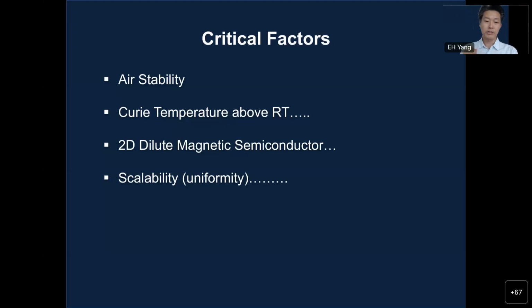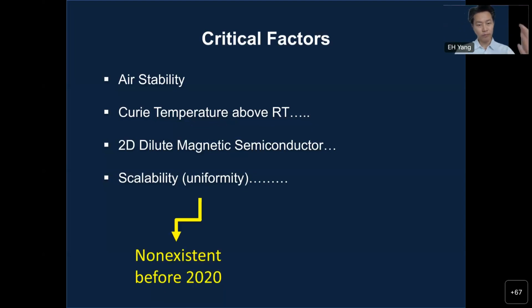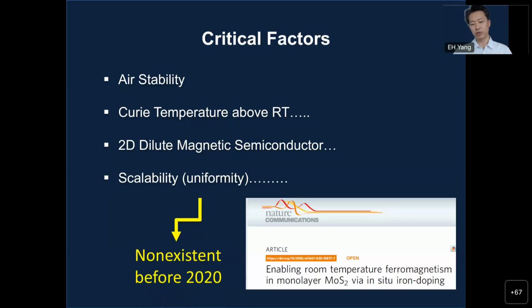Scalability: if you use the Scotch tape method to get these 2D materials or 2D magnets, it basically offers zero scalability. You need to provide scalability to some extent, and also uniformity of these materials. Okay. Now the problem here is there was none. There was no report that fulfilled all four requirements, all four critical factors, until we published our work in 2020. It's entitled Enabling Room Temperature Ferromagnetism in Monolayer Molybdenum Disulfide via in situ Iron Doping.